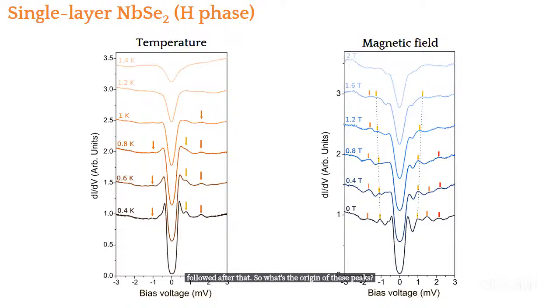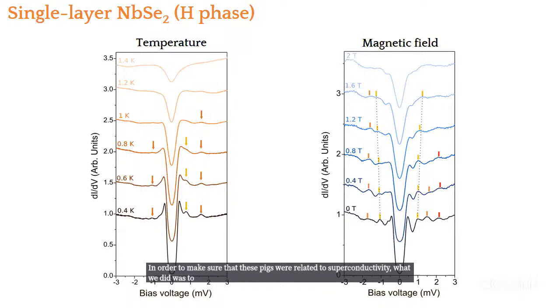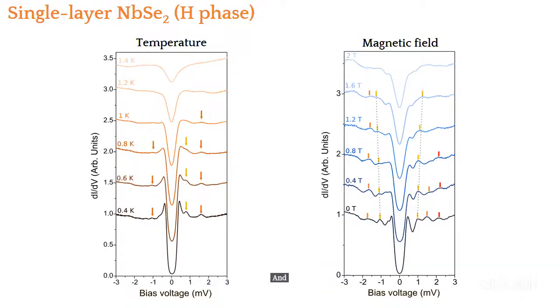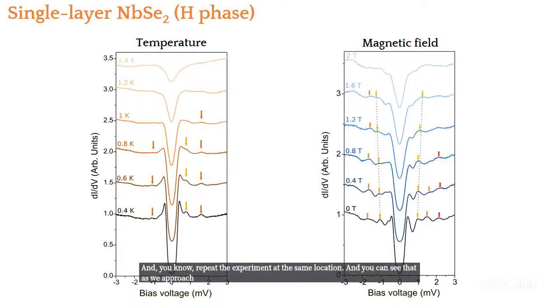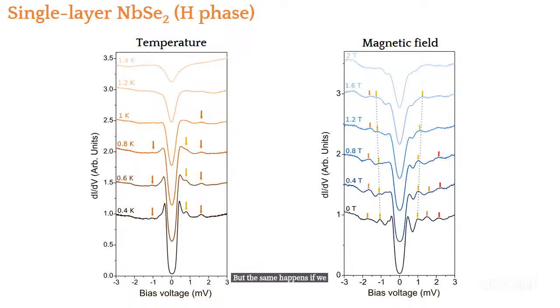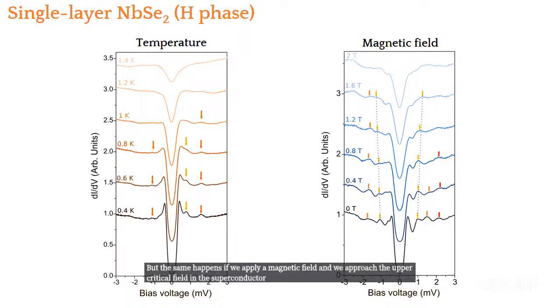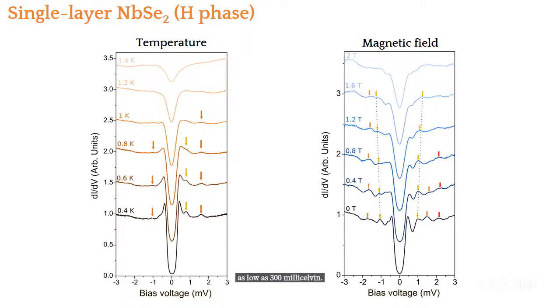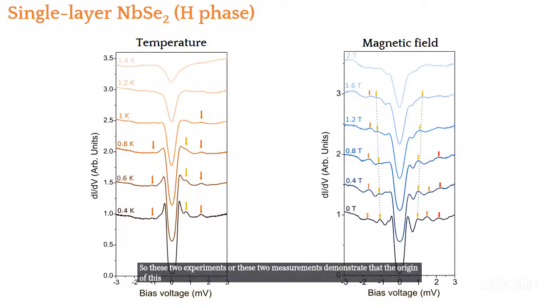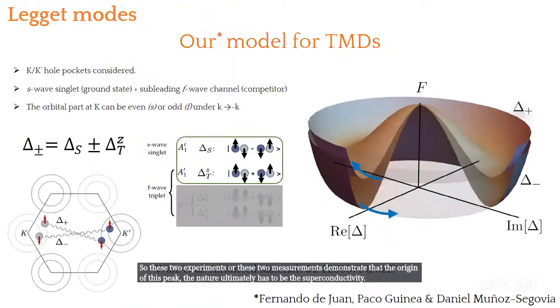In order to make sure that these peaks were related to superconductivity, what we did was to increase the temperature and repeat the experiment at the same location. And you can see that as we approach the critical temperature, basically these peaks are gone. The same happens if we apply a magnetic field and we approach the upper critical field in this superconductor. Basically, these peaks are gone, even at temperatures as low as 300 millikelvin. So these two measurements demonstrate that the nature of these peaks ultimately has to be superconductivity. They are related to superconductivity.